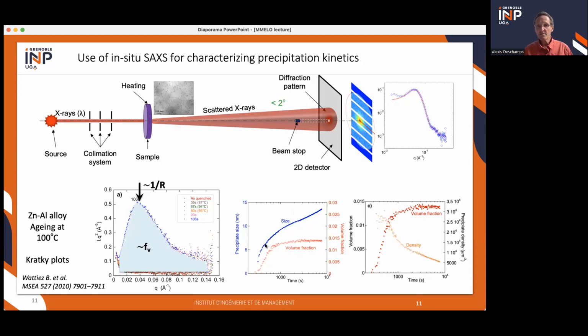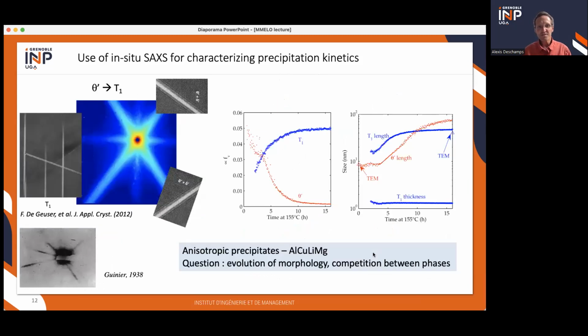And so it gives you a full description of the precipitation kinetics in a given set of conditions. We could comment later in the discussion, if you're interested, on why we usually don't see any nucleation stage. When you do these experiments, you always see a decrease of the density of particles and almost never an increase. But I have no time to discuss this in detail here.